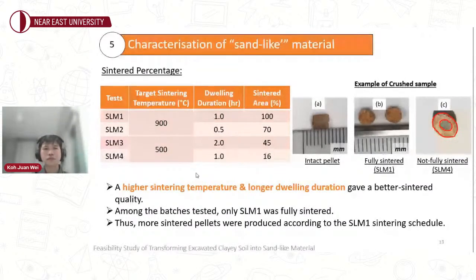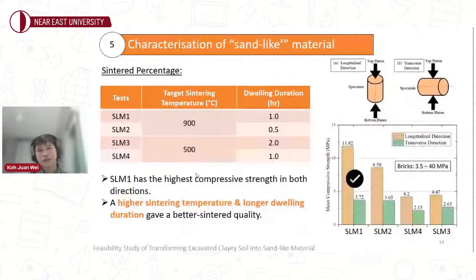Okay, the first test was the individual particle compression test. This graph shows the mean compressive strength of the material itself. As you can see, SLM1 with 100% sintered percentage produces a higher mean compressive strength compared to the others, and the value is actually comparable to brick material.